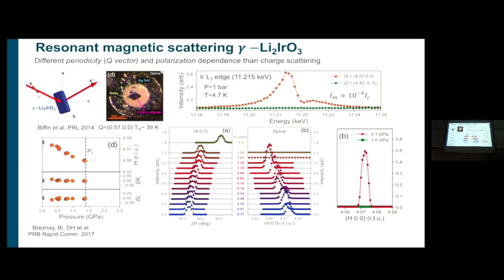So we can follow this under pressure, apply pressure. This is the 400 Bragg peak. As you compress the lattice, it moves to larger angles. And this is the magnetic Bragg peak, this incommensurate magnetic Bragg peak. You see that this incommensurate wave vector, which has to do with how the spins kind of lock to the lattice structure, changes with pressure. It becomes a little smaller, the peak shifts to the left, but then all of a sudden at 1.5 GPa, this peak disappears. And actually all magnetic peaks disappear, and magnetic order goes away. So you get very excited because you think, maybe we are going into the Kitaev limit, and you have to come to a talk tomorrow to learn what really happens here.